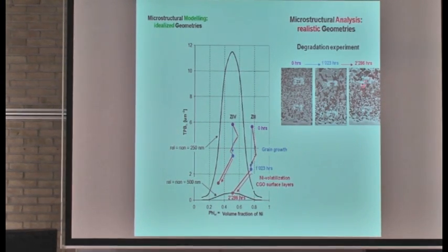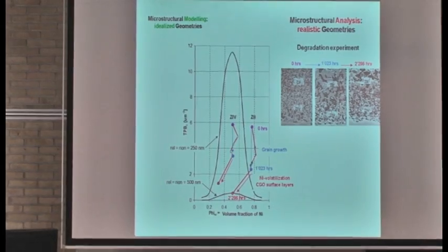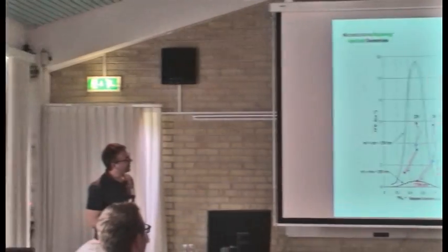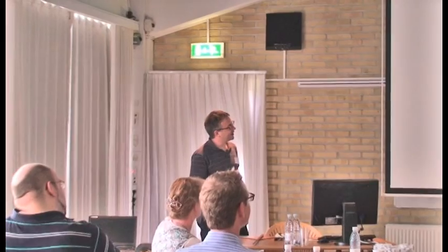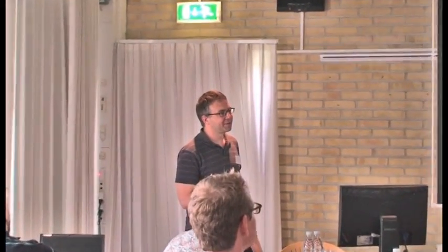And so what we get here is, I think, small particles are somehow going away. I don't know where, but then we get a passive enrichment of the ceramic phase because nickel is going away. The pores remain stable, so maybe there's some volume decrease as well.